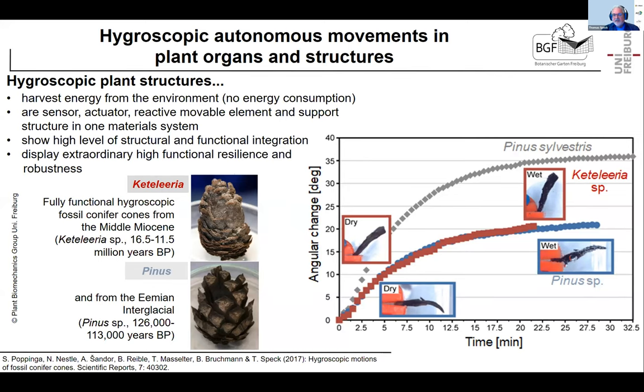We tested them here in the dry state and here in the wet state. You see that the angular change of the single scales shows exactly the same pattern as the extant living Pinus sylvestris scales. This shows us that even after 15 million years, these systems work. They still do their trick. First, it proves that there is definitely no living element involved. And secondly, it shows how robust and resilient the systems are.